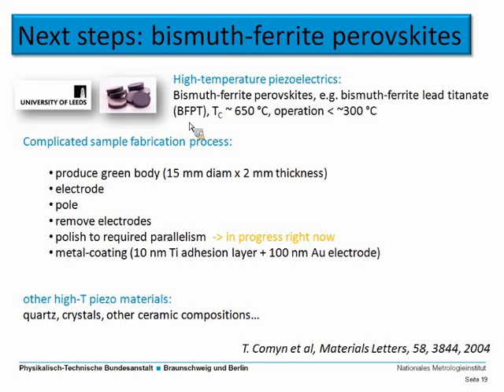The only drawback that we saw was that we have a complicated sample fabrication process. We have to start with producing the green body, so those discs with 15 millimeters diameter, 2 millimeters thickness. We have to electrode them, pole them, so that they get their piezoelectric properties. And then in principle you could say, okay, now we go and measure them. But remember those tight sample specs regarding parallelism and flatness that Guido mentioned.